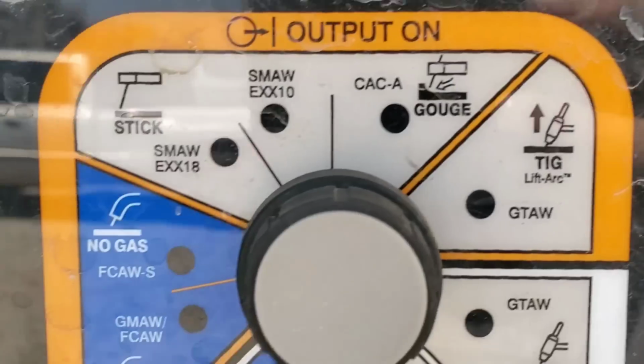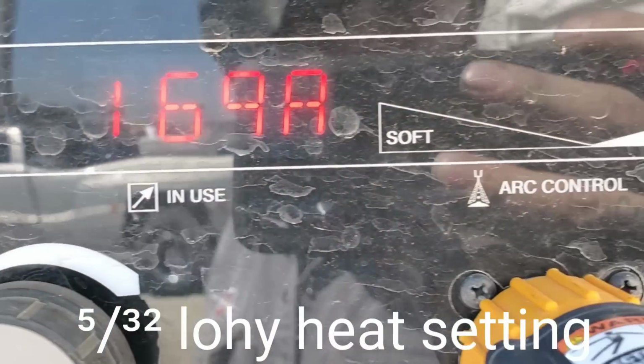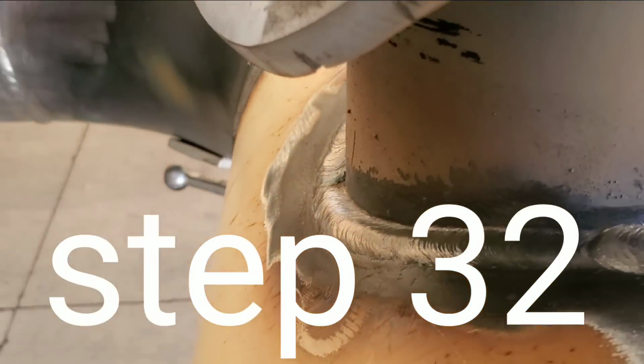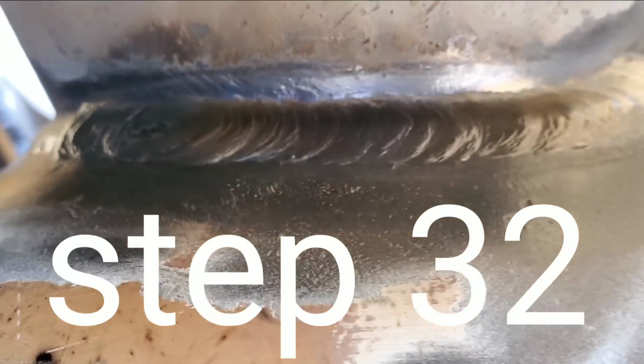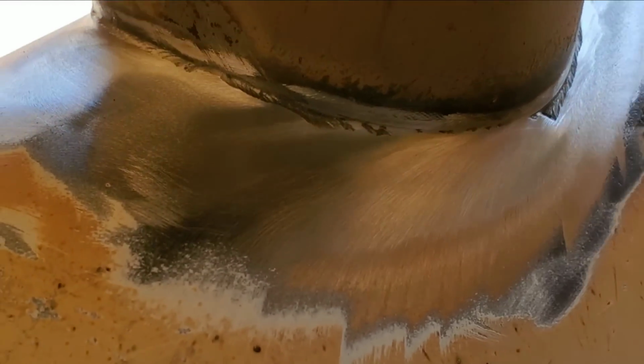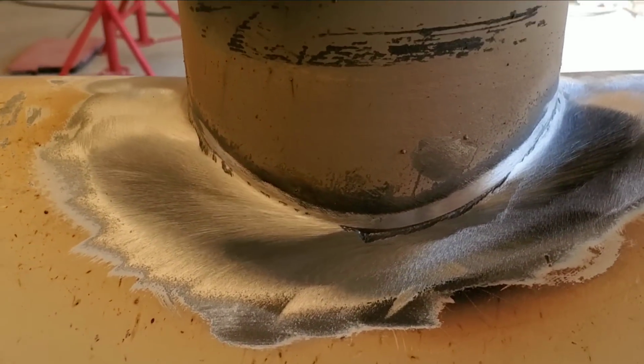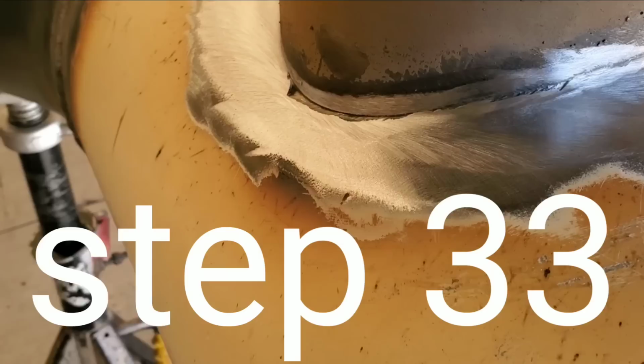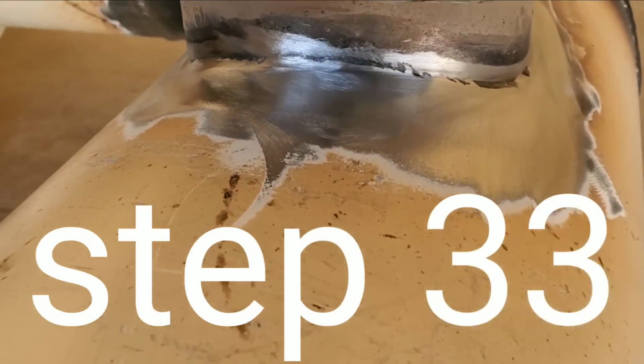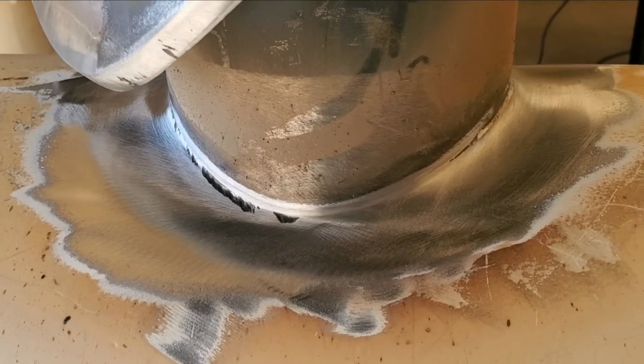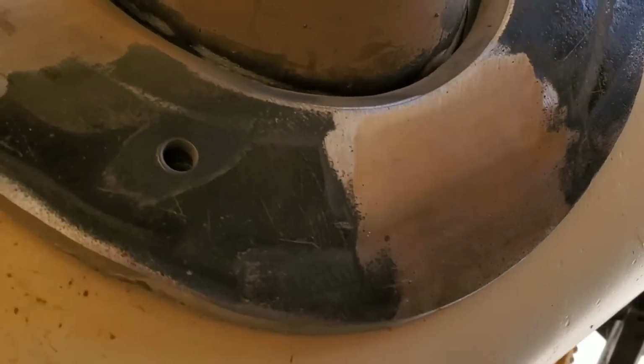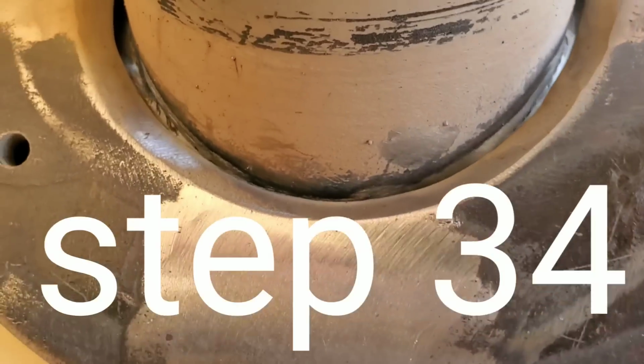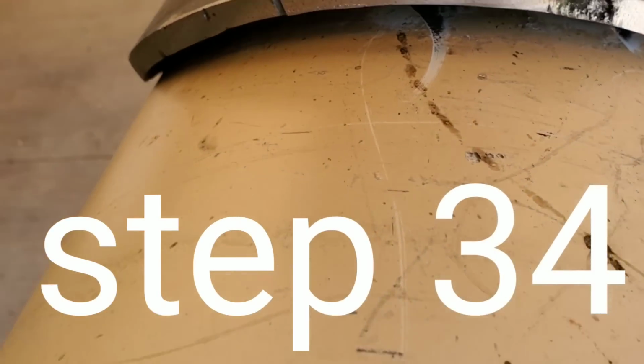Right here I go over the amperage, 169 amps on uphill mode on my Miller 400. 5/32 is the rod I was using. Step 32 is just verifying it to make sure you see nothing that is going to cause porosity or a crack. And then I move over to step 33, and that's grind it out completely flush with the pipe. There is a little bit of undercut on the top, but I'm not worried about it because I will be laying the repad down on it now and welding it out completely in the throat of the repad to make sure that I fill it all up. Then I'll move over to step 34, remove the repad again and clear all the paint out from underneath it. It's very important that you get all the paint out from under it.